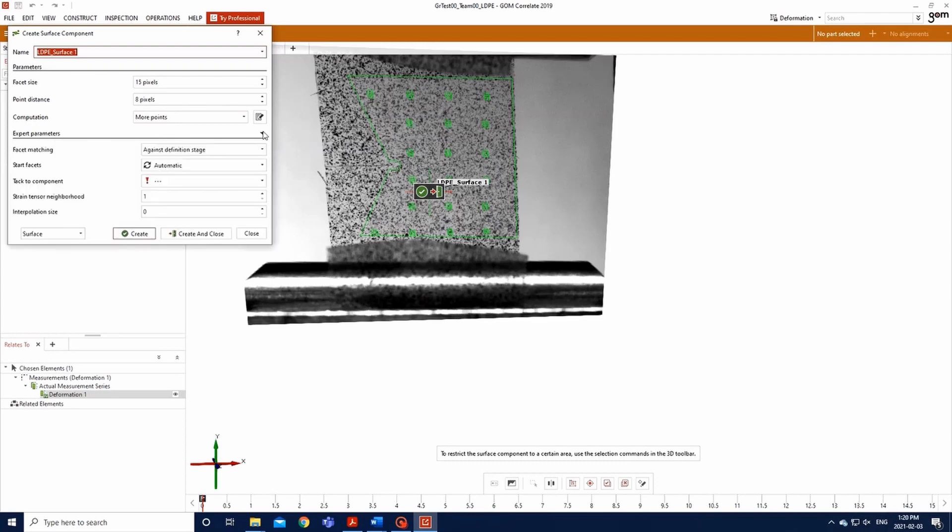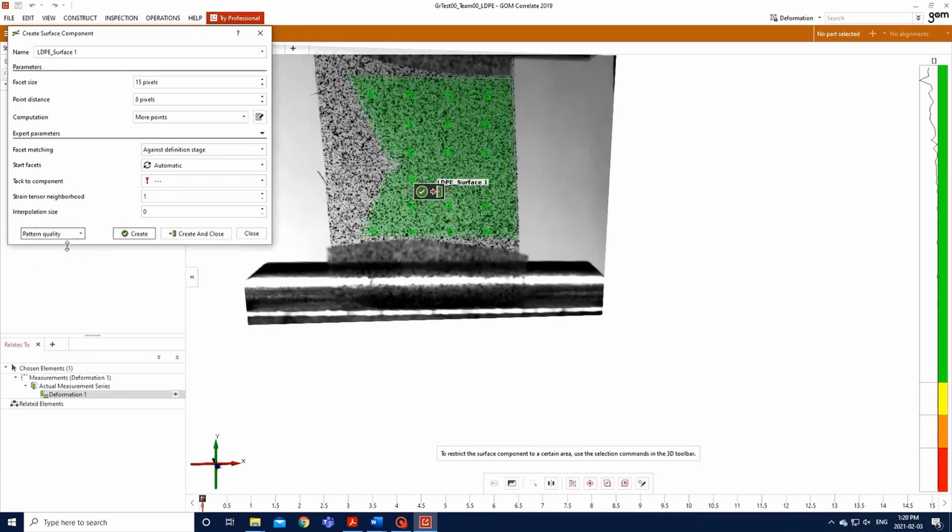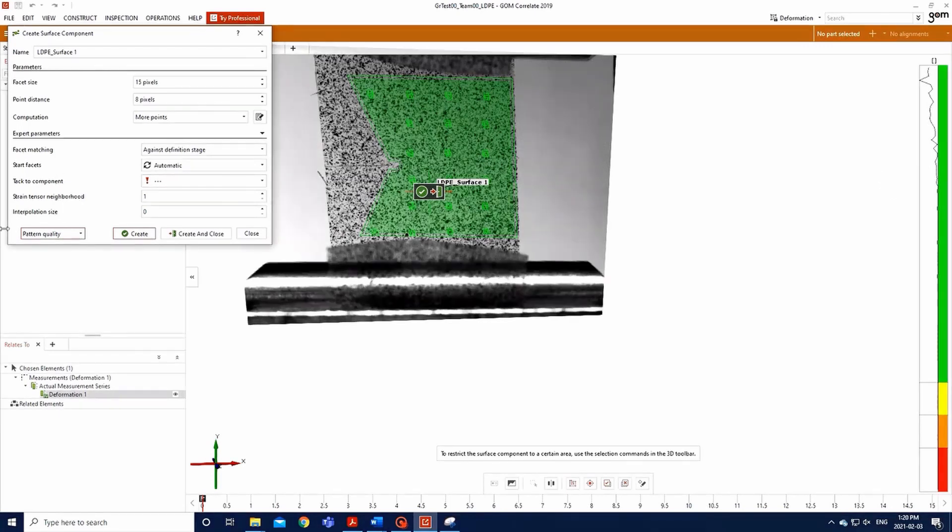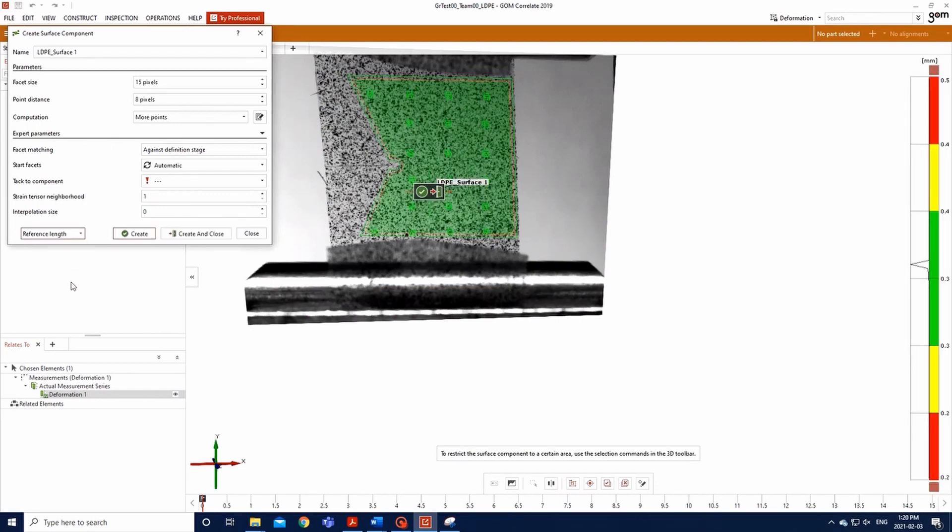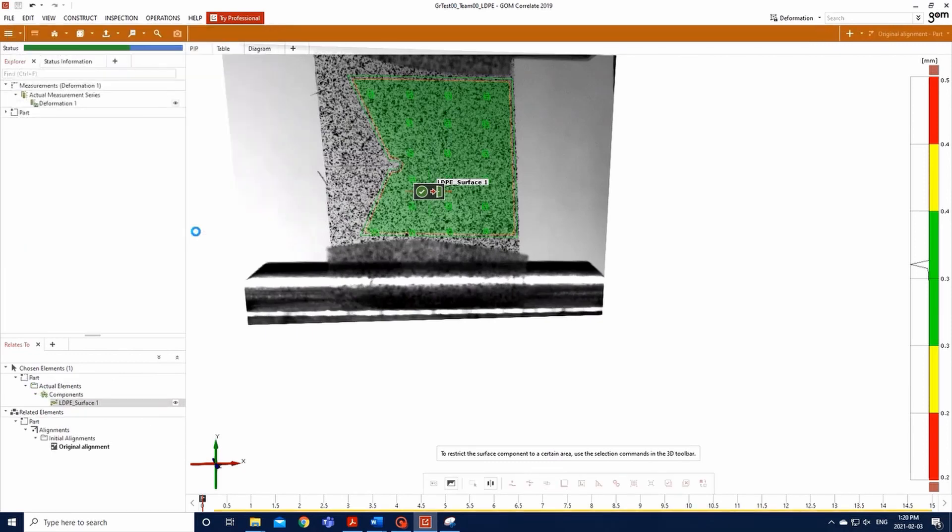Fill in the popped-up window according to figure in the lab module. To assess the quality of your stochastic pattern, select Pattern Quality. On the unrolling menu on the bottom left of the popped-up window, next to the histogram on the right side of your screen, there should be a continuous half Gaussian distribution in its green portion. This shows that the pattern quality of your image is good. Otherwise, refer to the lab module for adjustment. Take a screenshot of this step and include it in your report. You can also assess the reference length of your DIC analysis by selecting Reference Length in the same unrolling menu. Don't forget to report the value of the narrow Gaussian distribution on the left of the histogram. Finally, click on Create and Close.